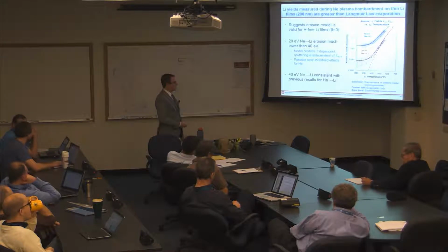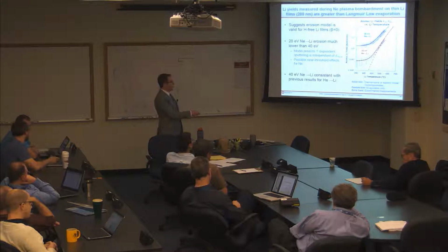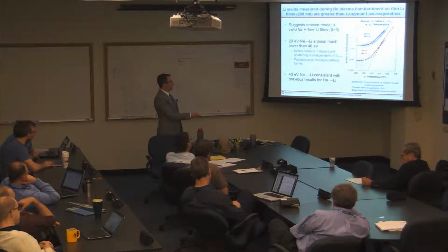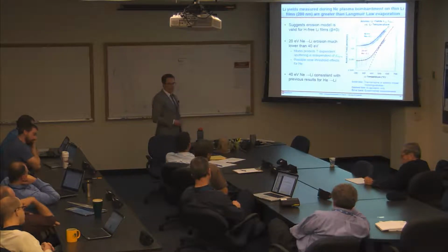It's pretty close to that, but it's not exactly that. I didn't plot just that, but the fact that you can see it's going up here, and since this is a log plot, this is still an order of magnitude below this, means there is a little bit of a thermal sputtering term.